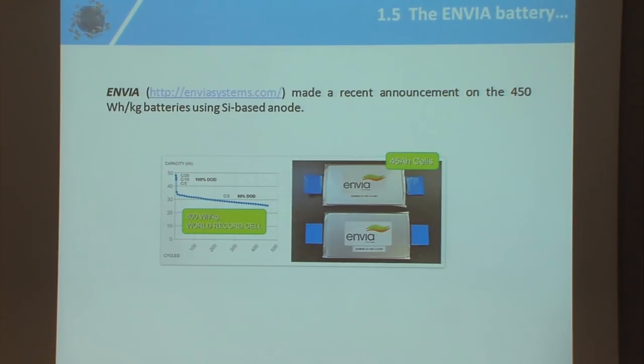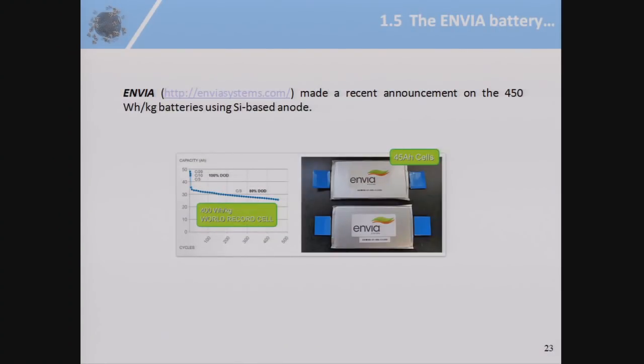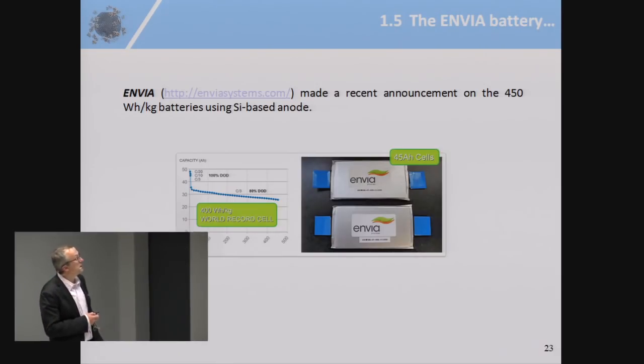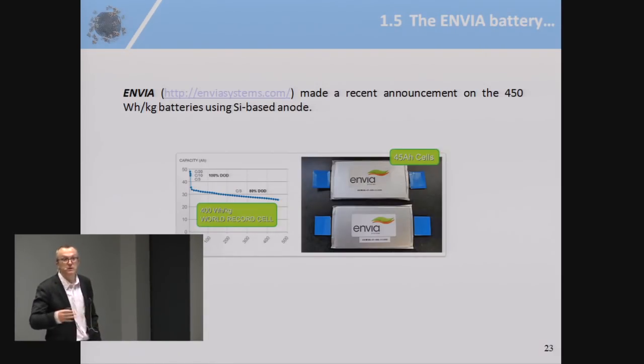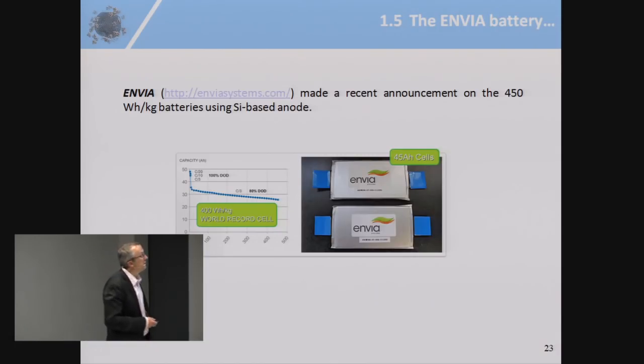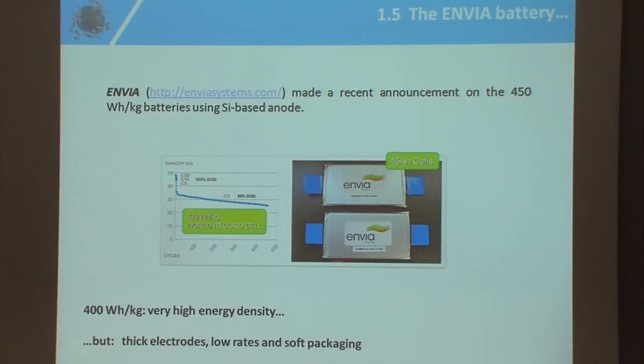And last, there was also, 18 months ago, an announcement from Envia Systems, 400 watt-hour per kilogram, a world record for cell of lithium-ion batteries. 400 watt-hour per kilogram, terrific. I mean, it's 2 times the energy density of lithium-ion batteries. What's the trick? In fact, there is no trick. They use a silicon-based anode. Fine, this is something which is in many labs. And also they use pouch cells, no aluminum case. So the weight of the packaging is very light.